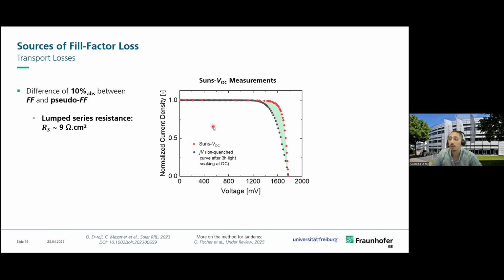Second, with regards to the fill factor losses, and more particularly the transport losses, we used suns-VOC measurements. So what are suns-VOC measurements? It's based on the fact that we vary the illumination intensity, and at each illumination intensity, we extract the VOC of the device, of the tandem solar cell. Now, since the measurement is carried out in open circuit conditions, there is no current flowing through the cell, and therefore the curve that we construct, the suns-VOC curve, or what is also called the pseudo-JV curve, is the same as the JV curve of the tandem cell, but without any series resistance losses.